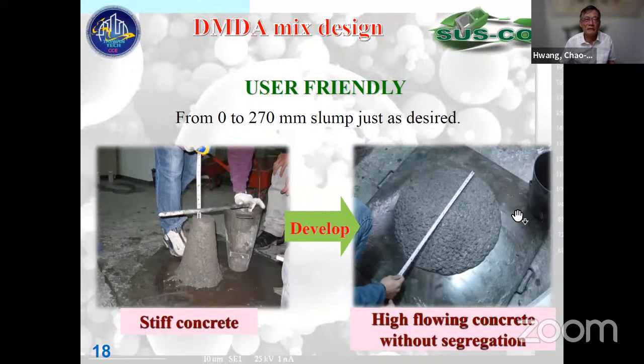If only using cement, it becomes very stiff. And the superplasticizer will lose its mighty power in 60 to 90 minutes. But with the fly ash, the concrete can last 2 hours to 3 hours, still flowing. So conventional concrete is very stiff. And then we can design the concrete slump from zero to 270 millimeter slump, just as we design. So you can design the desired flowing concrete with fly ash or bottom ash. Next, please.